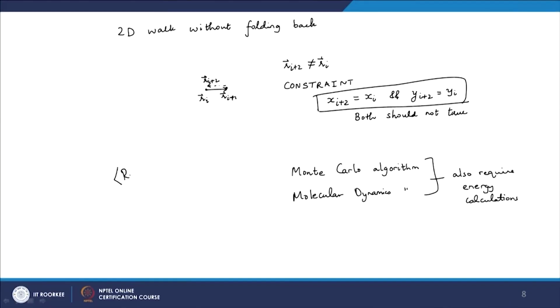So, you can write this kind of code in any language of your choice and try to visualize how the polymer chains look. That should give you the feeling of what we have covered in the class so far, that why are we saying that there are more conformations for lower values of R_e. This we should see by doing this kind of simulation. We can also establish the scaling law R_e squared proportional to m, and you would see that this would hold for large values of m.